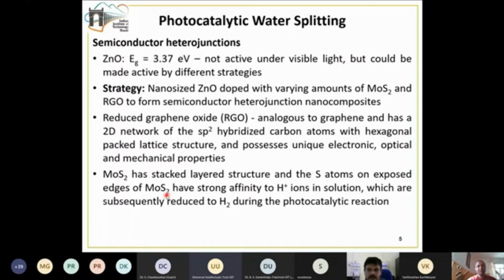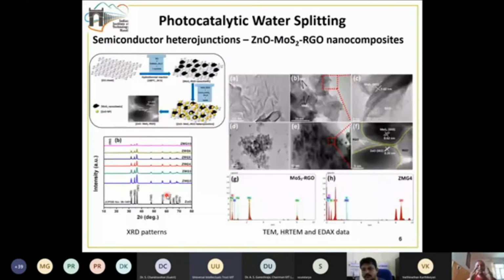After we decided that these three materials are good to make a nanocomposite, now comes how to make this nanocomposite. First we started with graphene oxide, GO, which is exfoliated from graphite, and then took this graphene oxide along with the precursors of MoS2, which are sodium molybdate and L-cysteine. We took these precursors along with graphene oxide in a hydrothermal reactor in order to obtain a MoS2-RGO nanosheet. We prepared this nanosheet in a 1:1 ratio, which means 50% of this material is MoS2 and 50% is reduced graphene oxide.